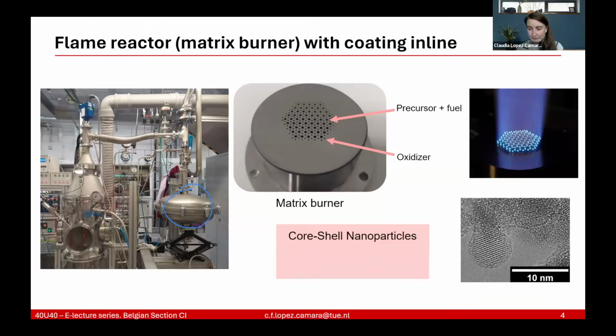The striped part of this nanoparticle that you see in the TEM picture on your left is the core. In this case, it is titanium dioxide, and the surrounding area of this striped part, which is amorphous material, is silica. Therefore, this nanomaterial is a core shell nanoparticle with a core of titanium oxide and a shell of silica. But with the same approach, we can also do iron oxides covered in silica, creating the iron oxides or the titanium in the previous case by the flame, and then covering them with jets that we will see in a moment.